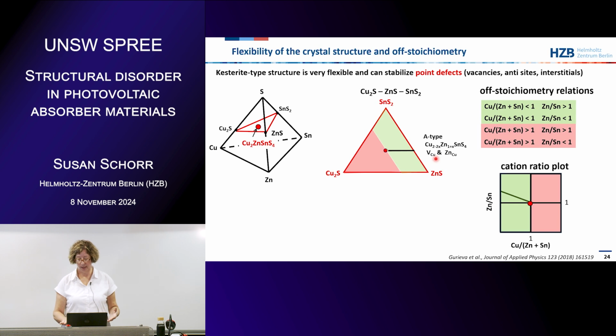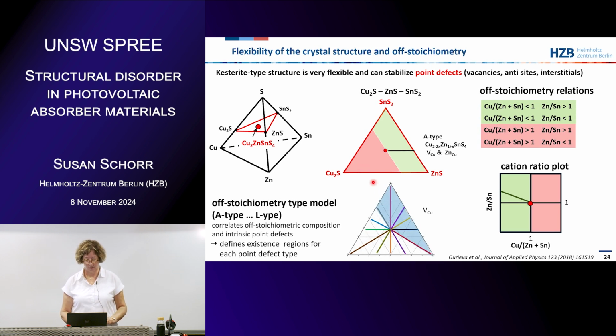And in principle, this was the A-type line. Each of these lines is one of these off-stoichiometry types, and each type correlates different point defects according to the chemical composition. And then you see in this area of the triangle, you have copper vacancies, for instance. This is the stability region for copper vacancies. Now this is a model, and we had to prove that.